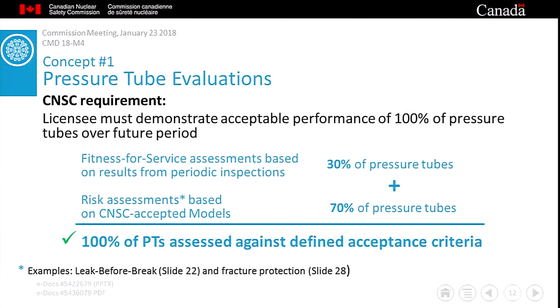Both leak before break and fracture protection assessments start from a worst case assumption that somehow a crack has occurred in a pressure tube without operators being aware of it. The licensee then calculates the probability that the hypothetical pressure tube will rupture. All of the assessments must meet the acceptance criteria established in the compliance verification criteria of the License Condition Handbook. Based on the results of these assessments of both inspected and uninspected pressure tubes, CNSC staff assembles a composite view of the safety of 100% of the core.